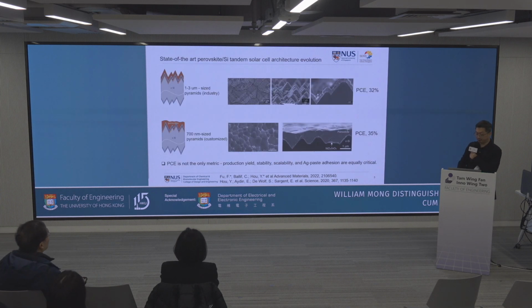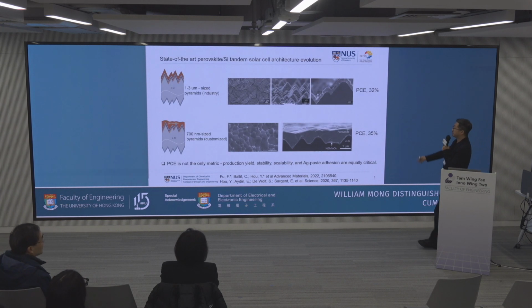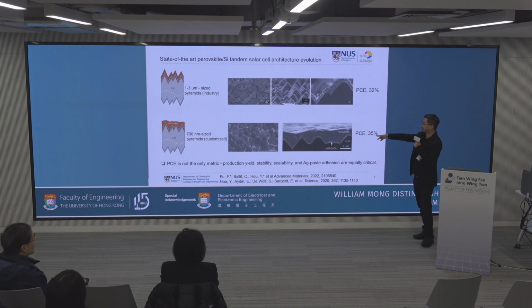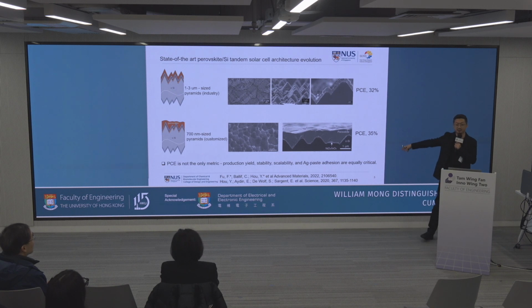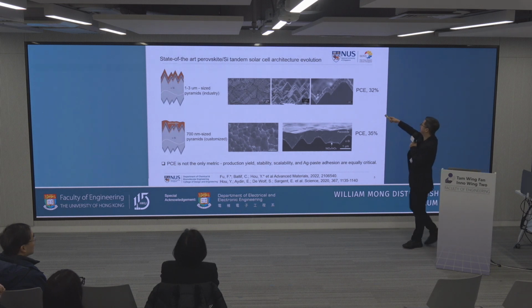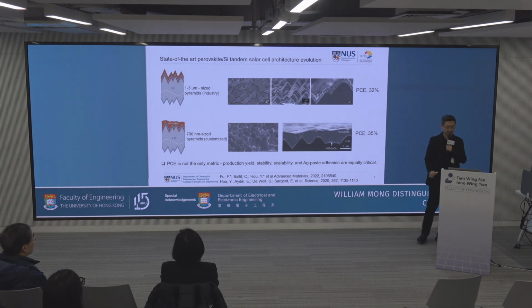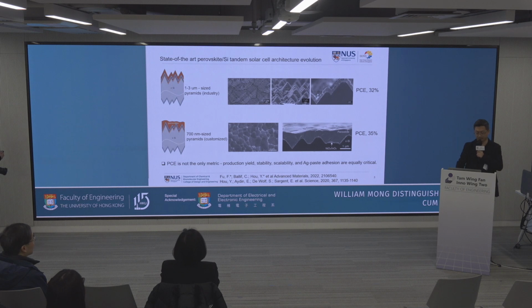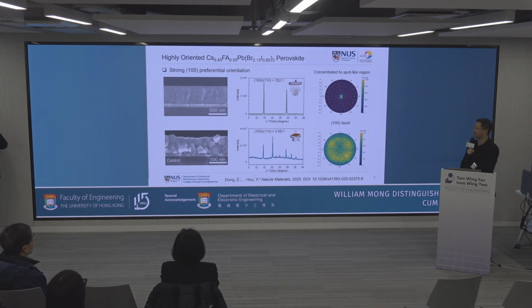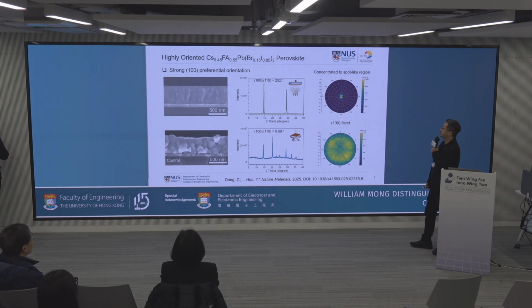And right now, if you look at this technology, it's solution processing, and the current record efficiency is actually based on this approach, 35%. With conformal growth on double texture, it's about 32%. So it's a more efficient technology, but it's not everything, because we find the stability is still a big issue for this.